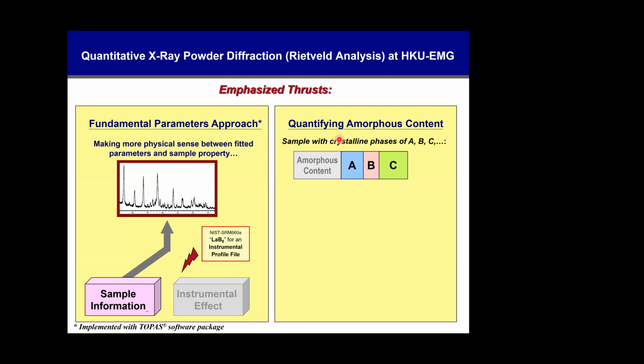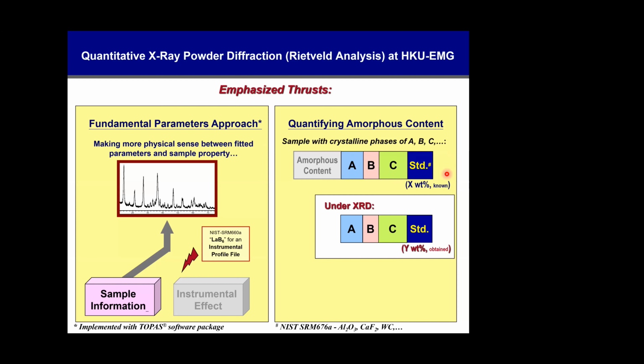In order to do so, you have to have an accurate fundamental parameter approach first, no problem. The second thing is that for the quantification of amorphous content, you've got to have a standard, an internal standard. Once you know how much internal standard you have, then you do the Rietveld refinement with the known crystalline phases that you found. And you go back to calculate, then you understand how much amorphous phase is actually there. If the dosed amount comes out exactly the same as your standard, you understand there's no amorphous content. Usually that's not the case from our experience. So the amorphous content needs to be quantified.